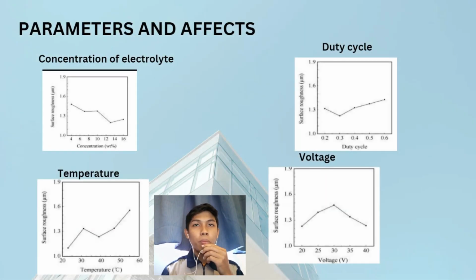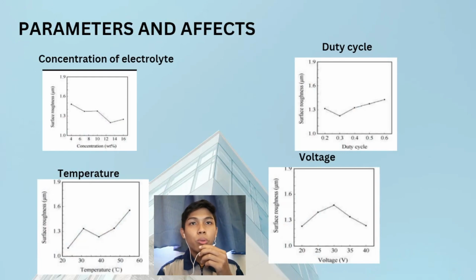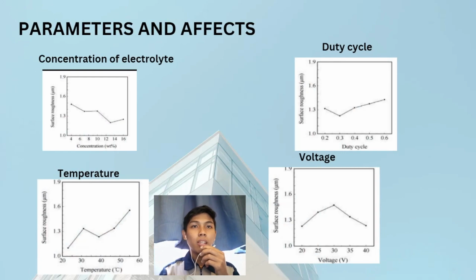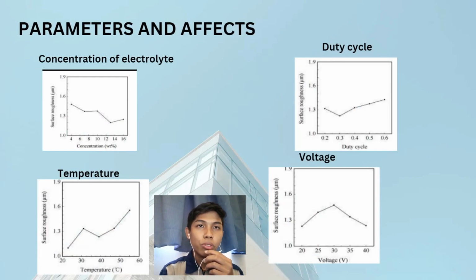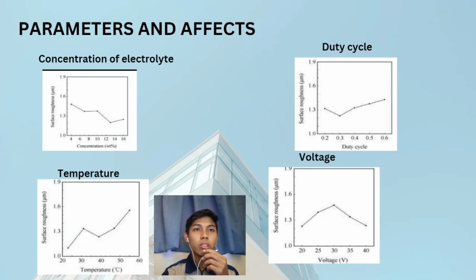Temperature. By referring to the graph, we can see that the surface roughness becomes poor due to the increasing temperature, and when the electrolyte temperature is higher than 50 Celsius the quality of the surface deteriorates. And as the temperature of the electrolyte increases, the specific resistance also decreases, and this can affect the flow rate and the pressure characteristic of the electrolyte.